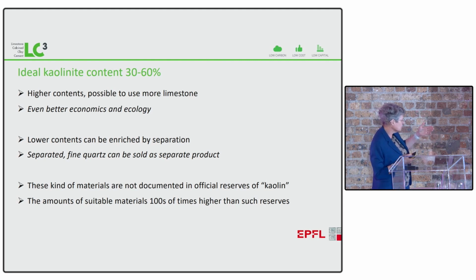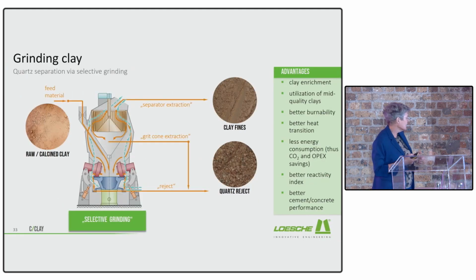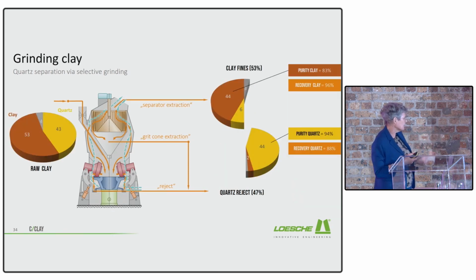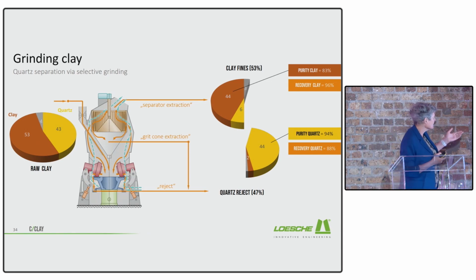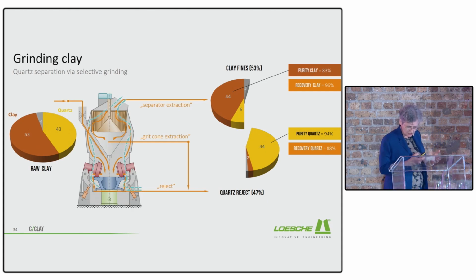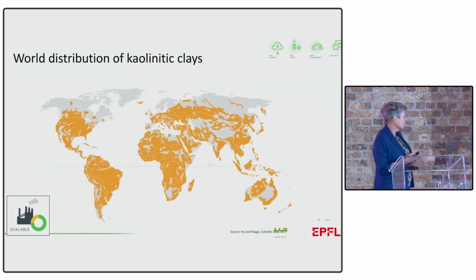If you have higher contents, you can blend in more limestone, which gives you even more savings. If you have lower contents, you can enrich it by separation. And we know Kaolin Group had developed their own separation route, but just to give you another perspective, these are a couple of slides I got from Loesche, who are doing the separation with the vertical roller mill. And they start with this mixture of calcined clay and quartz, and then they can really separate this with a high degree of efficiency. Here in the calcined clay, they end up with a clay purity of about 83%, and the quartz has a purity of about 94%. So, you have different methods which are suitable for different clay deposits, and it's clear that what the Kaolin Group are doing here gives a similar outcome.